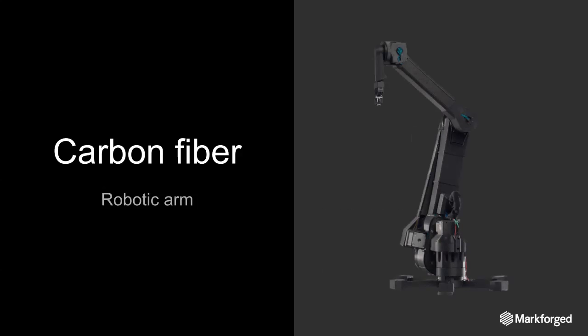This is one of our customer examples. It's a company called Haddington Dynamics, and they developed Dexter, which is a 3D printed robotic arm, and it's almost completely made out of 3D printed Markforged parts. They use carbon fiber reinforcement for the arm because it's the only material that's stiff and lightweight enough to keep the precision that they want on this robotic arm, which is 50 microns, just about 0.002 of an inch, is the precision of this arm in 3D space.